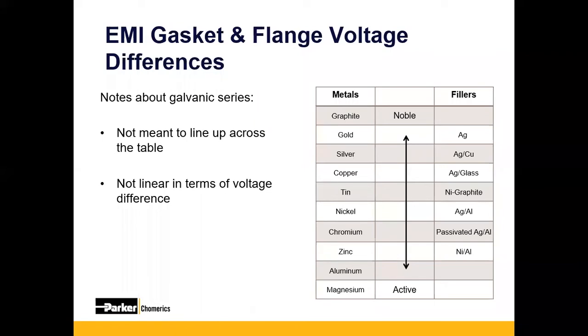So if you look here, you can see aluminum, which is a very common material in a lot of applications because of its cost, its weight, its workability, ends up being lower on the galvanic chart, which means it can actually take the most damage in a lot of systems. That's why you see the fillers on the opposite side, on the right side of the chart, used to make sure that you're getting the best possible interface and minimizing the difference in that potential.